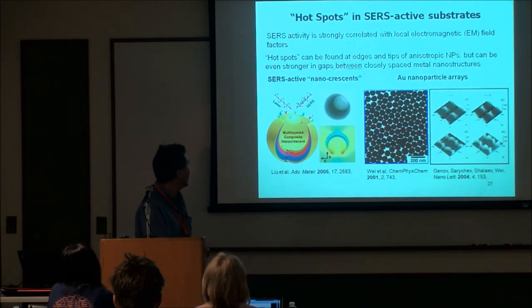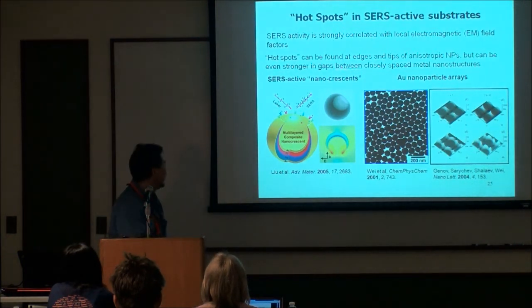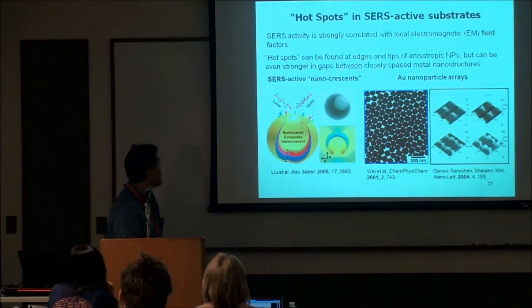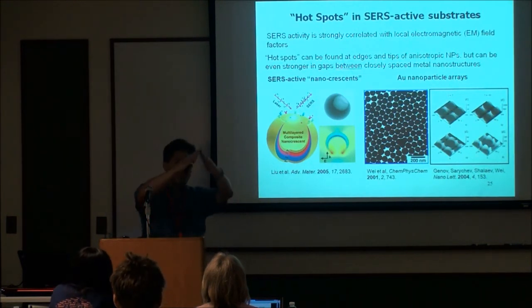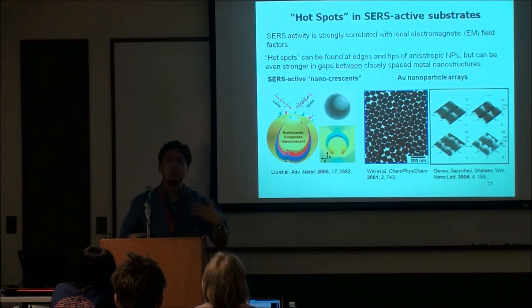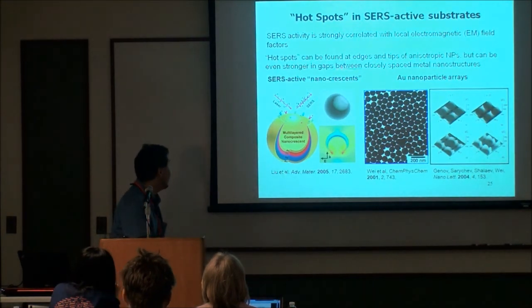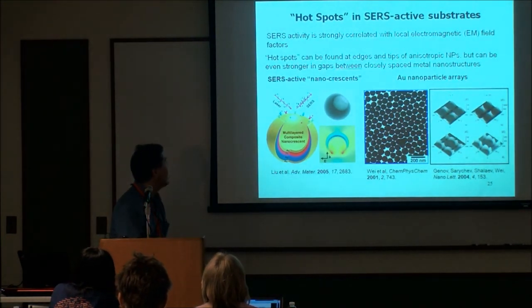And it also contains a magnetic component, so you can orient the particle, right? We really have this interest in combining magnetic and plasmonics together. But the key about this structure is that the way that it was designed is that you have a rim here, which is rather sharp, right? And because the gold on the inside and the outside come to a point, you can actually have a very strong field intensity right there on the edges of this kind of structure, right? So if you functionalize this with antibodies, you're able to detect things like SERS signals of molecules that bind to that center, okay? This is one of many, many different examples, but I think it's a very cool example, okay?